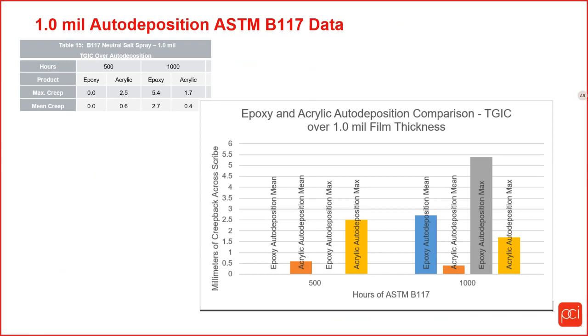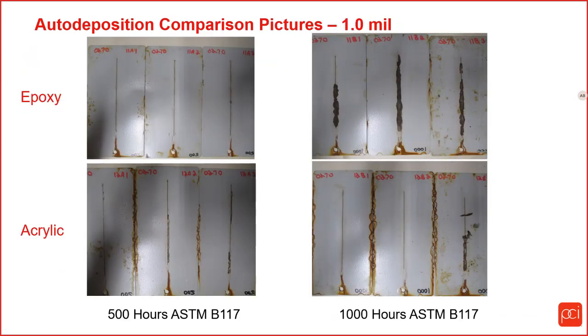And here is the 1 mil auto deposition. So for this one, the 500 hour salt spray, the epoxy did better than the acrylic. And for the 1,000 hour salt spray, the acrylic did much better than the epoxy. And once again, here are the pictures for that particular test.